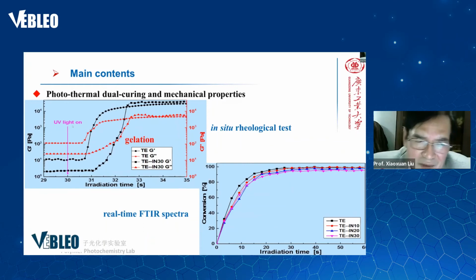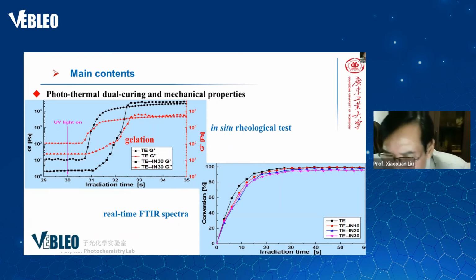This is when the UV light is on, at the beginning of exposure, in situ rheological testing. After the UV exposure is on, the relaxation of the system is very different. It is increased. So this is the real-time FTIR spectrum: the double bond conversion is quick, up to 90%. Very, very high conversion.